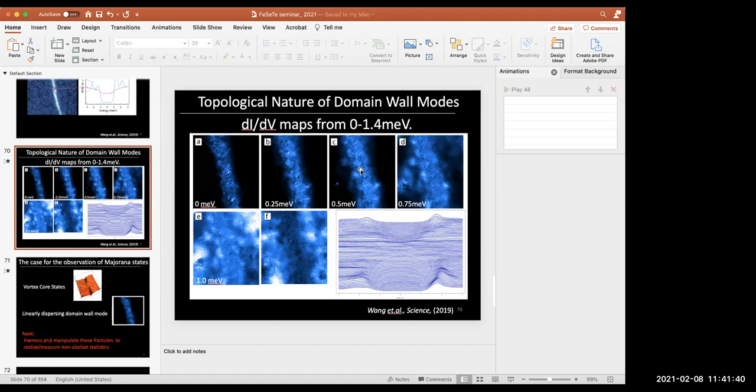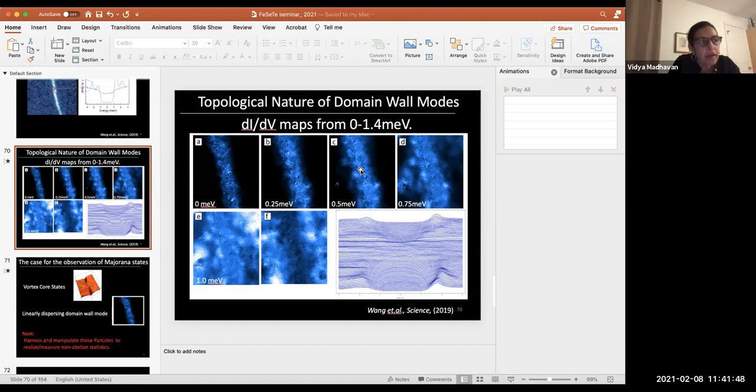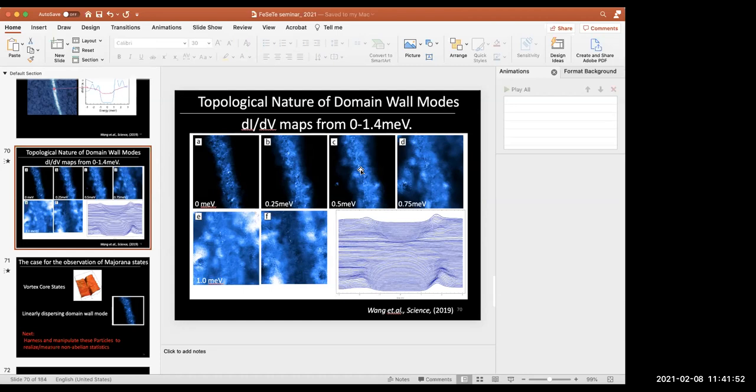This goes back to the comment one of my colleagues made earlier, where we were talking about the fact that Majoranas always come in pairs. Now, in the 2D limit, you obviously don't have two ends of your vortex. So either your vortices come in pairs, or the localized Majorana in the vortex core can pair with the delocalized Majorana in the island state. So I was wondering if you had any small islands, whether you would see any interesting periodicity with magnetic field in the average spectra in your domain walls, which could correspond to different numbers of Majoranas being present inside the walls as a function of magnetic field as you add and remove vortices.